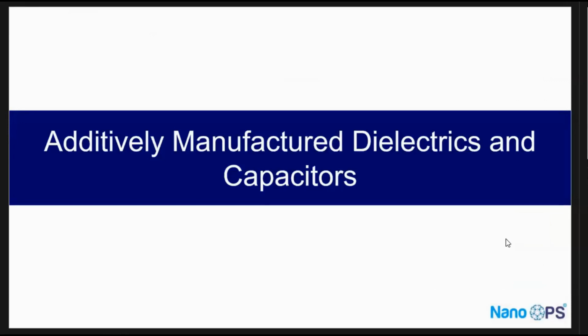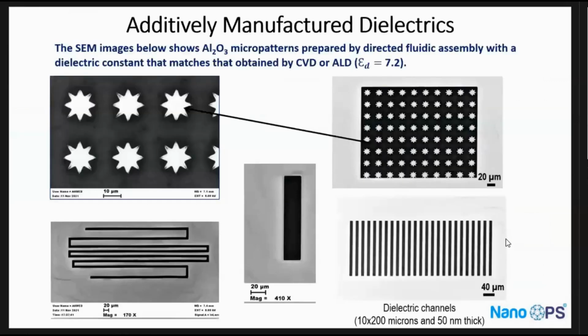Then the next step is to make fully printed capacitors, fully printed capacitors using inorganic dielectric, not organic dielectric. So in this case, the first thing we wanted to do is figure out how we can print inorganic dielectric. In this case, this is alumina, and you can see that we made a lot of patterns here just to test a variety of shapes and thicknesses and so forth. And so this is alumina.